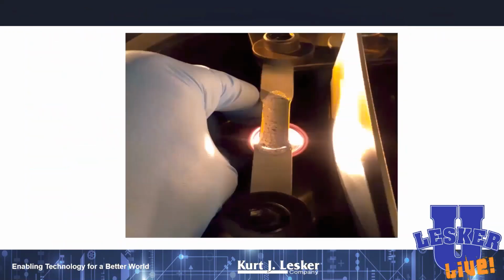Now, as I mentioned, these boats are consumables, and they get attacked pretty readily by molten materials. I think this is a tungsten boat that maybe had aluminum in it, and you can see that the molten aluminum ate a hole through the boat after a certain number of depositions, caused a crack there again. So these things are consumables. Just know that when you buy them, I think we sell them in packs of 6 or 12 or something like that. We think that you're going to get a deposition or maybe a few depositions out of them before you got to change them.